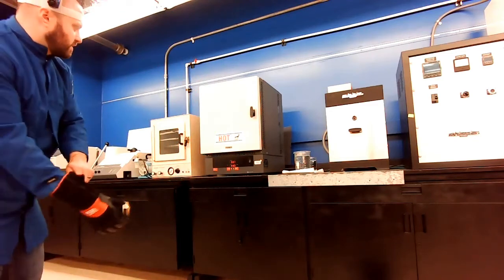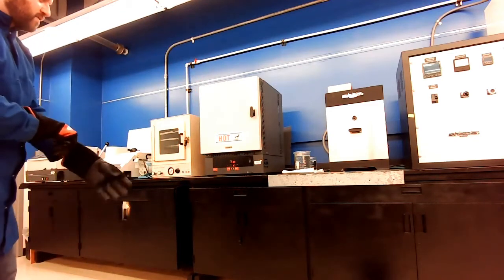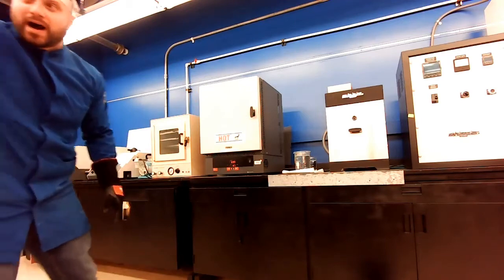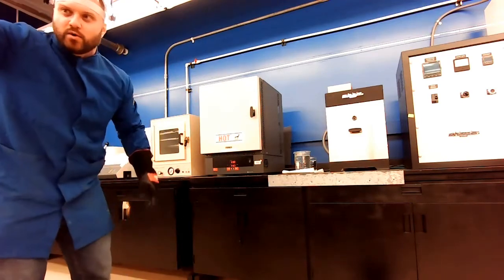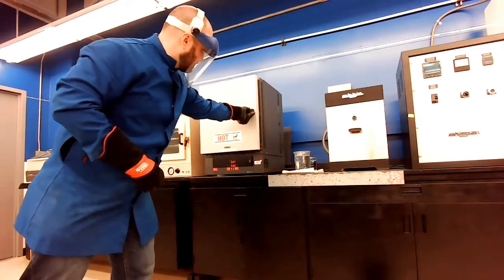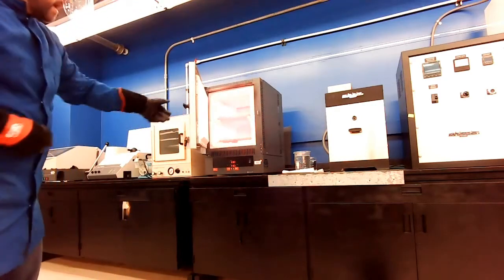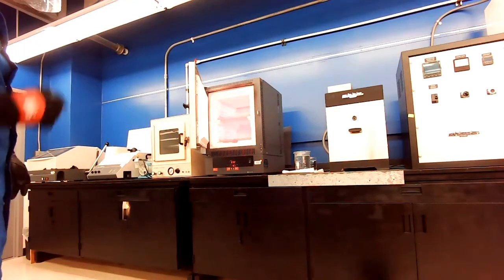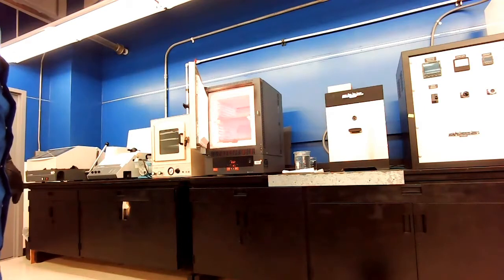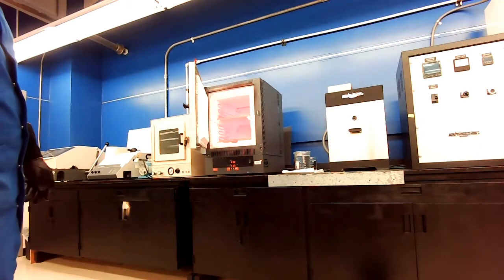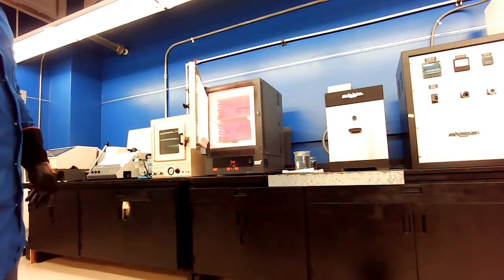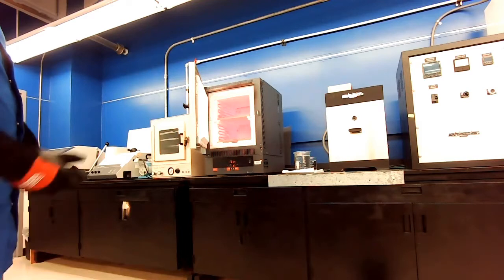Down to that 650. And actually my furnace is telling me something's wrong because it's too high, it's higher than the set point. That's okay, I know that's happening. So I'm going to pop this open. The temperature in that furnace is very rapidly going down. So it's at 850. See that that's very hot. Sitting here, I can feel all the heat coming off.